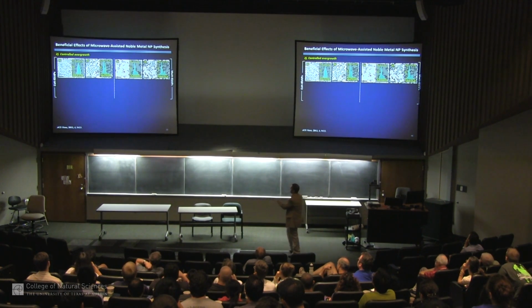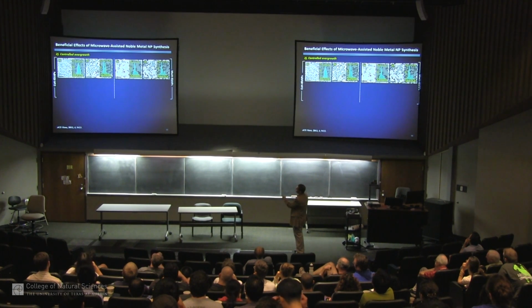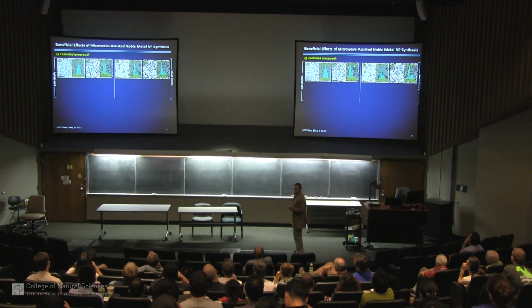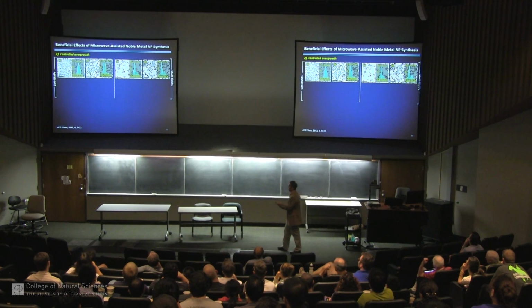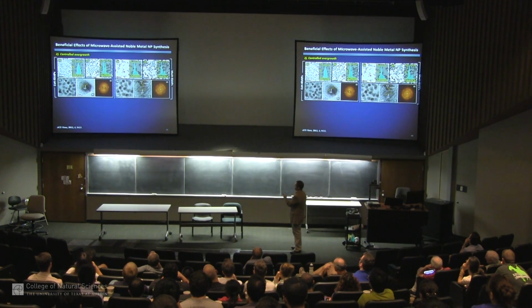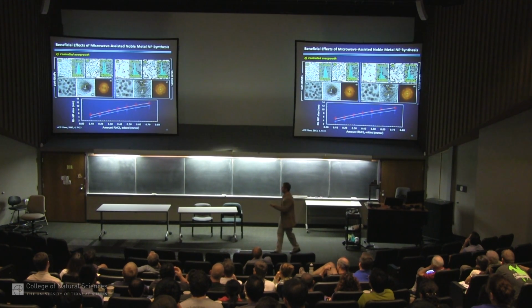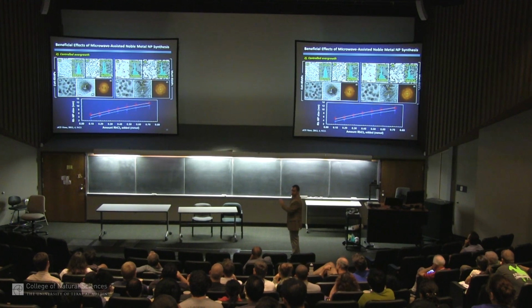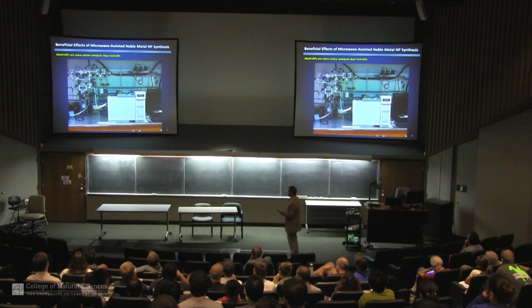and so therefore you've got all of these different surfaces exposed. Whereas in the microwave case, we can make, well, you can see this very well, a majority of tetrahedra, or we can make a majority of cubes. This works with about 90% selectivity, which is pretty good in this area, by using the microwave heating. And again, these particles, when you look at single particles from the microwave, are much more highly crystalline. So it's faster, and it makes more effective particles, which is all we were looking for. You can also dial in the average size of your particle simply by how much precursor you add. So it's completely simple at this point.